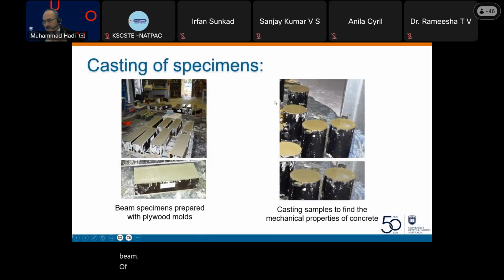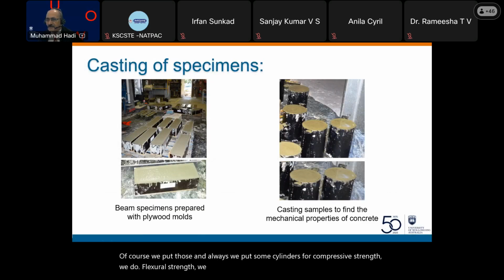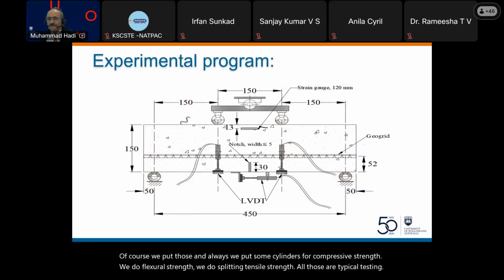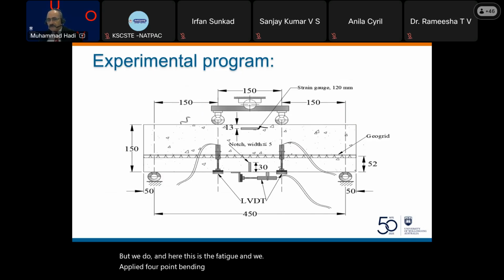Of course, we always put some cylinders for compressive strength. We do flexural strength, we do splitting tensile strength. All those are typical testing that we do. And here, this is the fatigue, and we applied 4-point bending, and the span was 450, and the geogrids are just over 50 millimeter from the bottom, and we put a notch less than 5 millimeter width to simulate the crack, and its length is 30 millimeters.